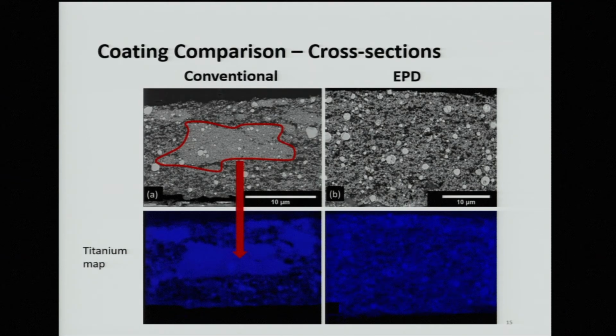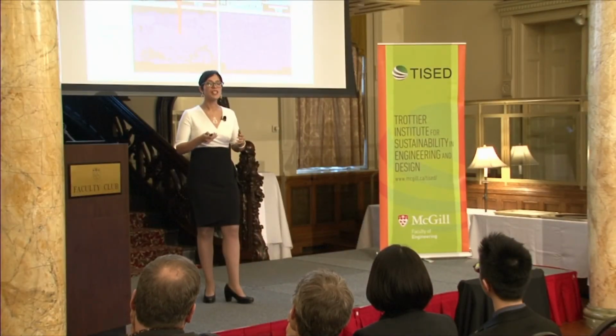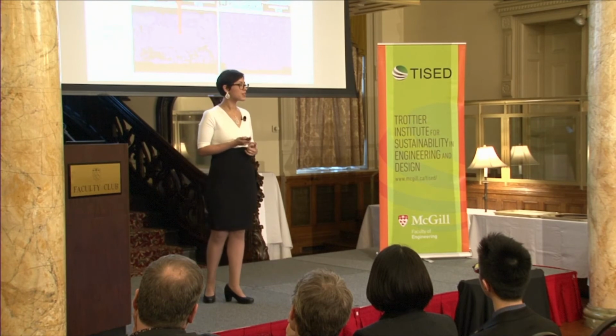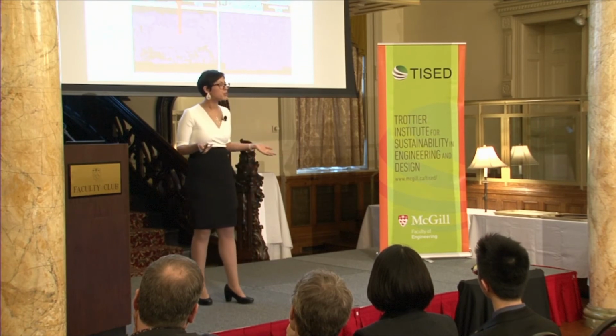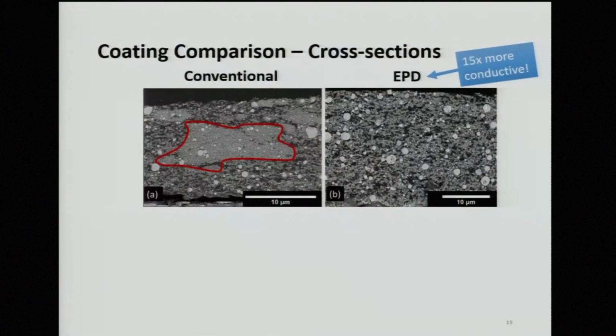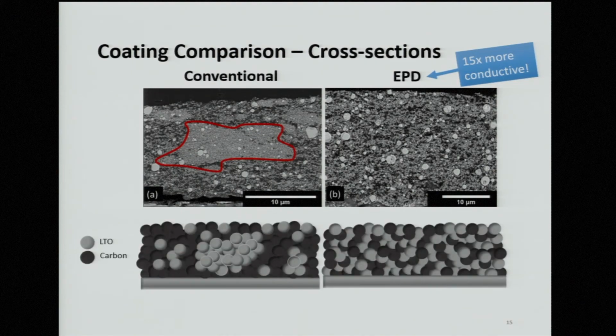Now, if you remember what I said earlier, the conventional fabrication technique doesn't make very uniform electrodes, and now we can visually see that. So we can say, so far, that EPD produces very uniform electrodes that perform really well at fast rate. But what is the connection between the uniformity and the rate performance? Well, we measured the conductivity of both of these electrodes, and we found that the EPD electrode was 15 times more conductive. So let's look at a schematic of these coatings.